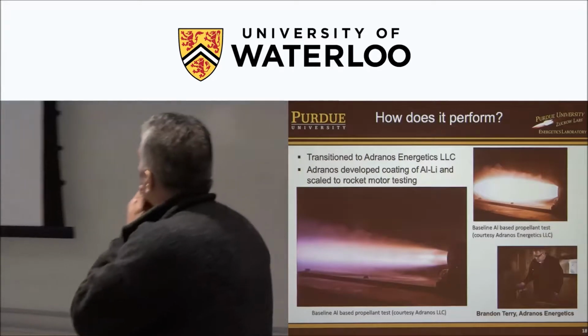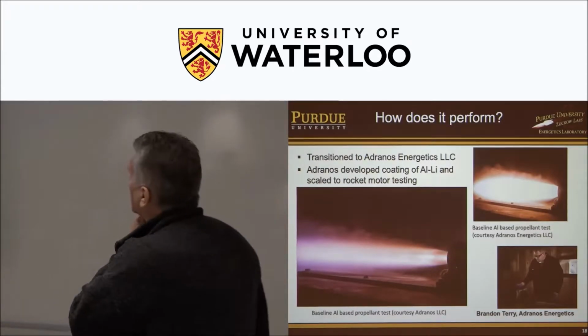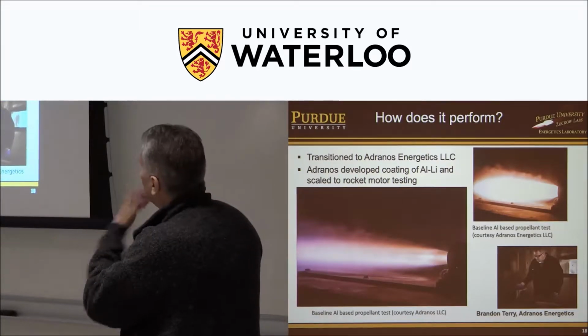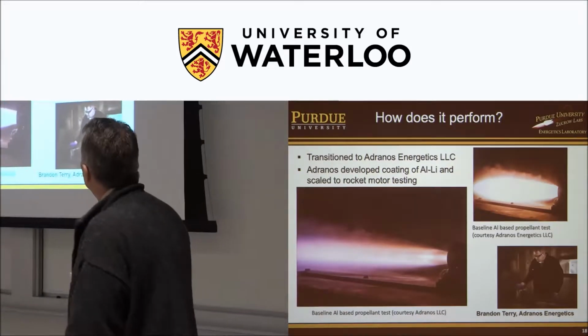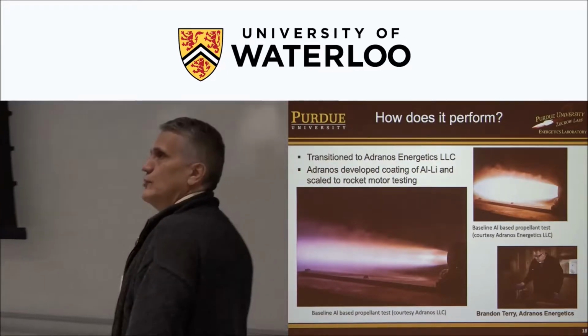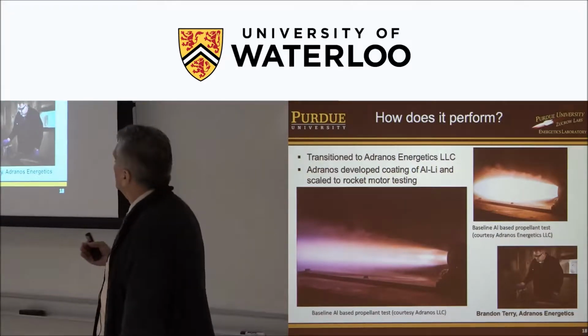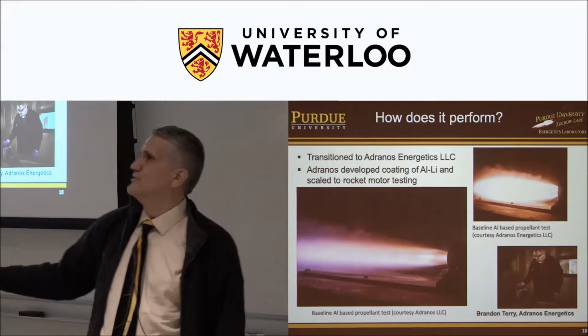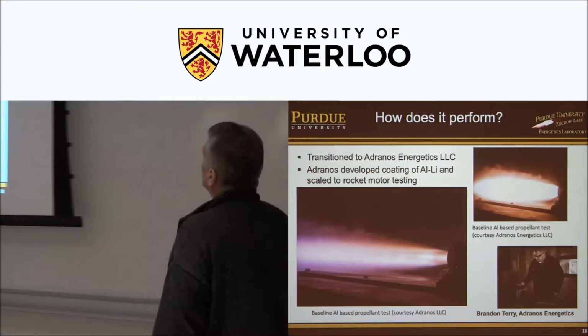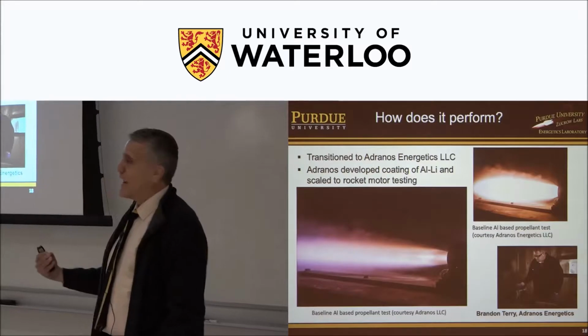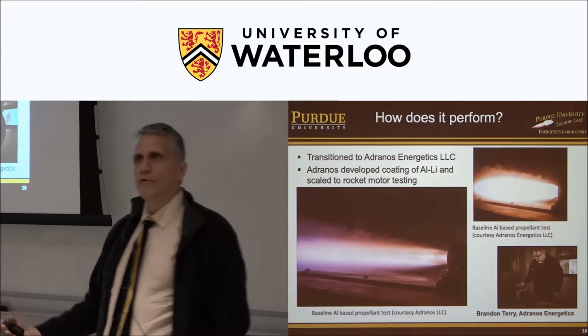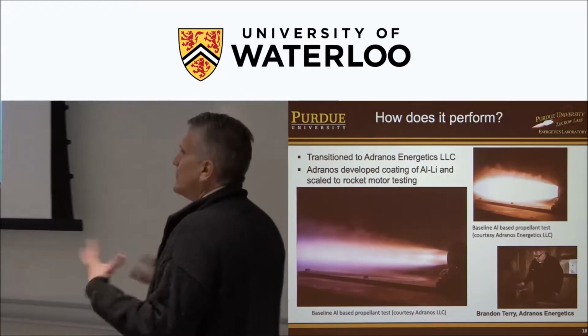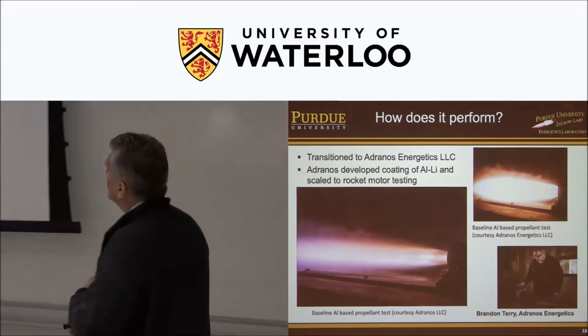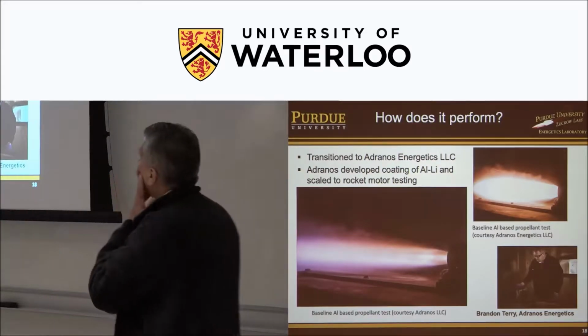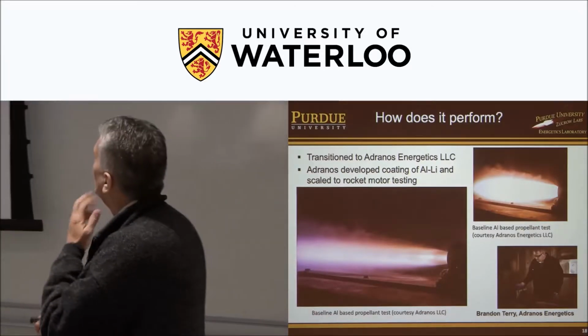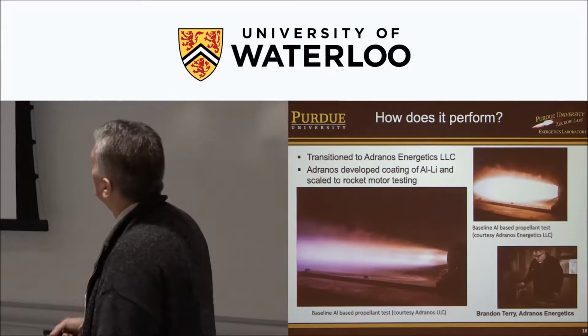A former student of mine started a company, Adranos Energetics. This is Brandon Terry, who's the founder of the company, and he's transitioned this technology to doing rocket motor tests. He developed a coating of the aluminum lithium. When we did our work at Purdue, we used uncoated aluminum lithium. As you might imagine, if you know anything about lithium or sodium, those kinds of metals, they're very, very reactive. In the alloy, it's more protected. The aluminum helps protect it, but moisture and air will still degrade it and slowly react it, so it makes it unsafe to scale to a rocket motor. And so he developed a coating of those alloys and scaled it to rocket motor testing.